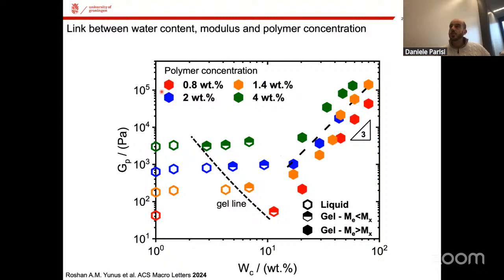So we can have a diagram where we plot the elastic plateau modulus as a function of water concentration. We can see these plots as a phase diagram, because different colors relate to different polymer concentration, or initial polymer concentration. Empty symbols mean that the solutions are liquid, whereas half-filled symbols are materials that became gels. But in this case, there are two plateau moduli. One is dictated by the entanglements, and another one is dictated by the crosslinks.